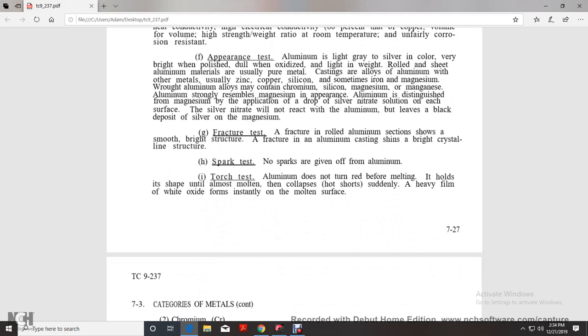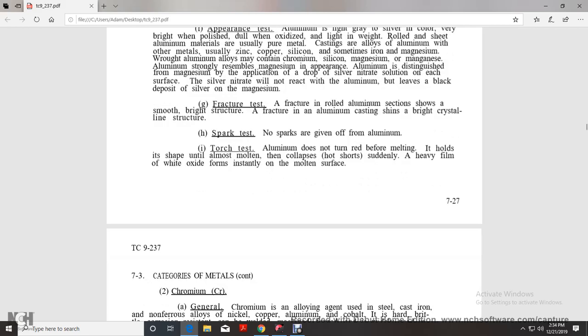Spark test: no sparks are given off from aluminum. Torch test: aluminum does not turn red before melting. It holds its shape until almost molten, then collapses suddenly. A heavy film of white oxide forms instantly on the molten surface.